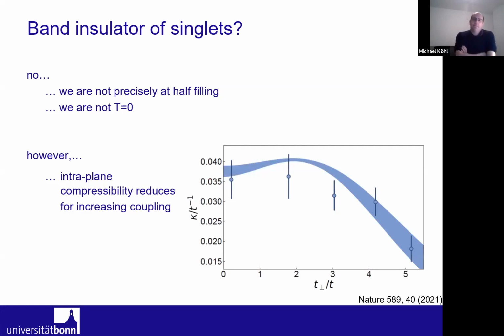And now we come to the question: what is actually the state of these singlets? If you're talking about the quantum critical point, then it was shown that the singlets would actually form a band insulator. So it's not just singlet pairs, but really an incompressible phase in the plane that is composed of these singlets, which are between the planes. And the question is, can we actually see that there is a band insulator of these singlets? And the answer, unfortunately, is no. Firstly, we're not precisely enough at half filling. We're at a filling of 0.45 or something like this. And we're not precisely at zero temperature.